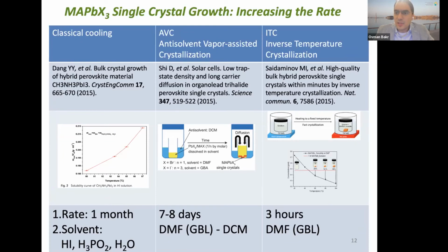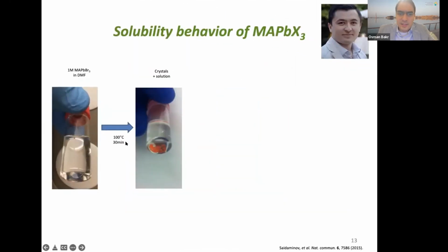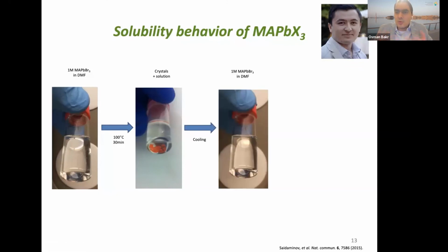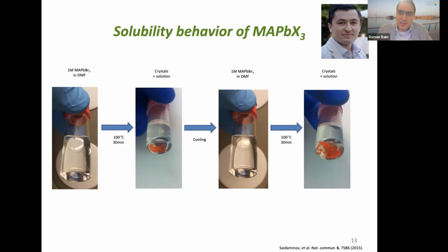We call this method inverse temperature crystallization. It started with a simple observation from one of my students, who noticed that when you dissolve your perovskites in a coordinating solvent and you start raising the temperature, the perovskites, instead of dissolving more, start precipitating. So if you cool down the solution again, you dissolve the perovskites, but if you heat it up, the perovskites precipitate. That's counterintuitive to what you normally would see when you dissolve, for example, sugar in water. When you raise the temperature, more sugar dissolves, not less. Here, the opposite is happening.